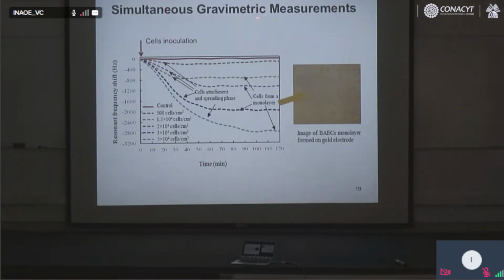Here, what is here? Resonant frequency shift. Yeah, here is the same idea. You have different concentrations of the cells, and the highest concentration of the cells is producing the highest resonant frequency shift. If the cells are more concentrated, that means you have more cells there, and then the cells are coming down and attaching very strongly on the substrate. And so, because the cells are heavy, the resonant frequency shift is a bit higher.